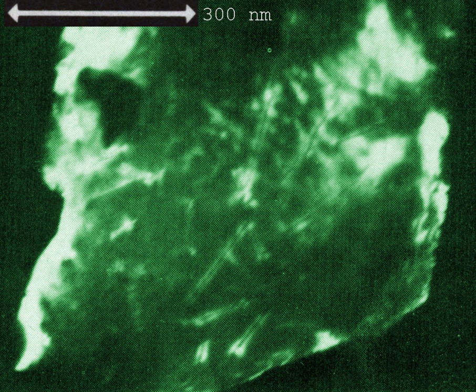Due to the large proton-to-electron mass ratio, the energy of the projectile decreases gradually and the projectile path is straight. A small fraction of the transferred energy remains as an ion track in the solid. The diameter of the ion track increases with increasing radiation sensitivity of the material. Several models are used to describe ion track formation.